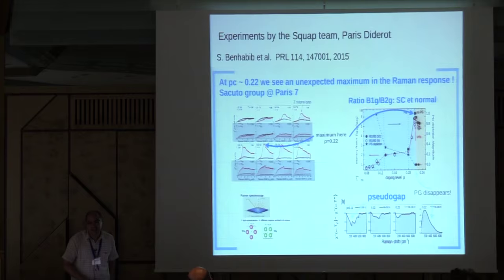So what they have done, and I really sketch, sorry, is that they took Raman measures for different dopings up to the overdoped side. Hopefully you see, because I see that it's not so clear. So this is underdoped, and this is overdoped side. And what they've noticed is that there is a clear increase of the spectral intensity at the value of the doping here, which is this one where you have this peak, around 22% doping. So we are strongly overdoped. So this is unusual. It was a very difficult experiment because what they are getting is absolute measures. So the setup is really complicated.